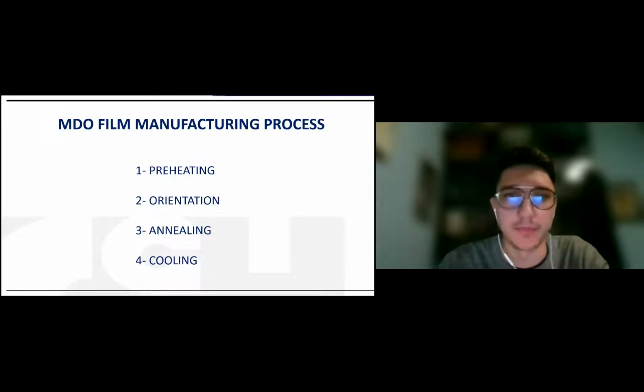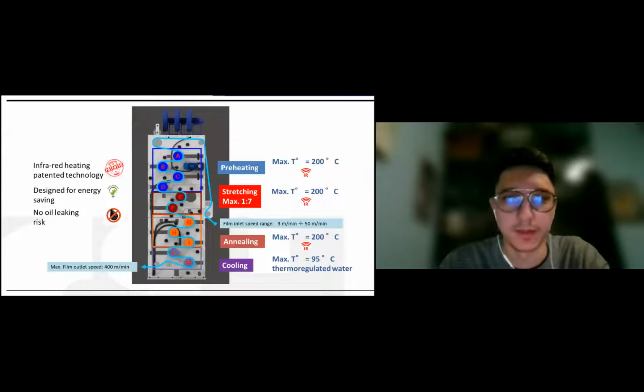This is how the MDO film manufacturing process works. So we have the pre-heating section, orientation, that is the stretching section, annealing and cooling. Here you can see the Colines MDO unit, where the film goes in this way, then entering the MDO section with the preheating section, where the film is preheated to achieve the temperature that is needed in the stretching unit. This is the core of the MDO unit, where the film is stretched and gains its properties. Finally, the annealing section is the section where the film is stabilized and maintains the properties, and then the cooling section before entering the treating section and the winding section.